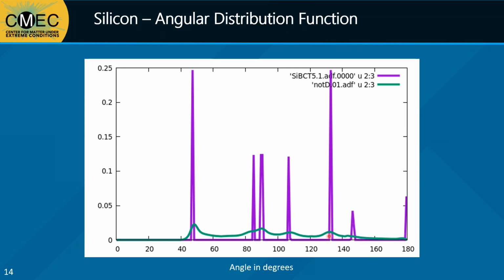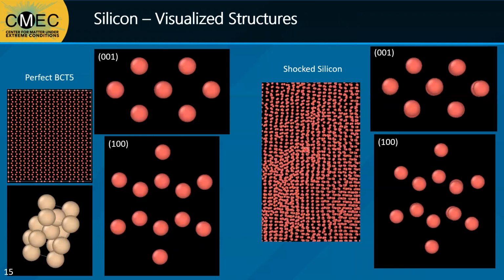Here we can see that each of the peaks within our pristine BCT5 sample and our shocked silicon sample match up perfectly, although the shocked silicon sample is understandably more spread out. To confirm that this match was accurate, I went into the simulation to plot individual structures from both the affected regions of the shocked silicon and the pristine BCT5 structure. On the left here, we have the perfect crystalline structure of BCT5, and on the right here, we have the shocked silicon sample. The top views and the side views both match up nearly perfectly, although there is some wiggle room for the atoms in the shocked silicon sample due to thermal effects and the strain present within the simulation.